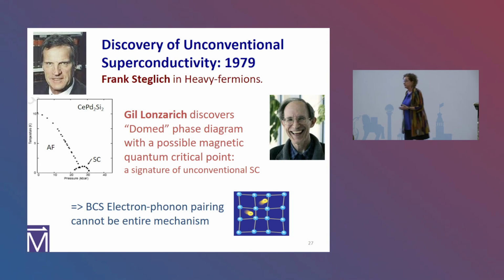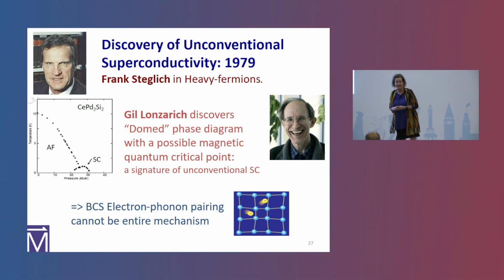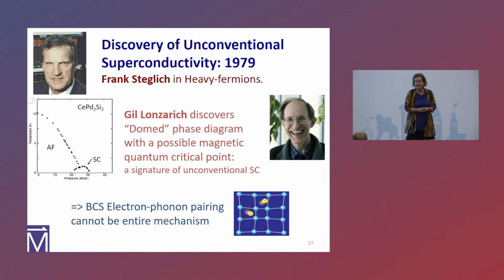But then these 2 geniuses, Frank Steglich, discovered something called heavy fermions, and heavy fermions, I mentioned them earlier, are materials that, due to electron-electron interactions, not electron-lattice interactions, the mass of the electron measured thermodynamically is huge. The one that I was growing thin films with was cerium copper-6. It had an m-star of 1,000. The one I'm studying a lot now is 85 or 120, but you can't get that from the band structure.